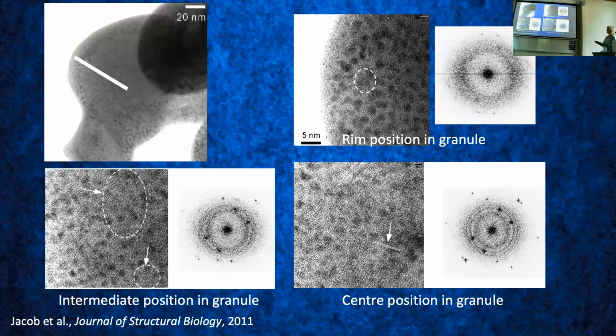Then we moved further inside, and the further we went inside, the more dots we found on the diffractogram, meaning that we're getting more and more crystalline things. So we could actually show that this is in fact an artifact. We had actually started to crystallize it under the electron beam. And you have to be really careful to not create artifacts like this.